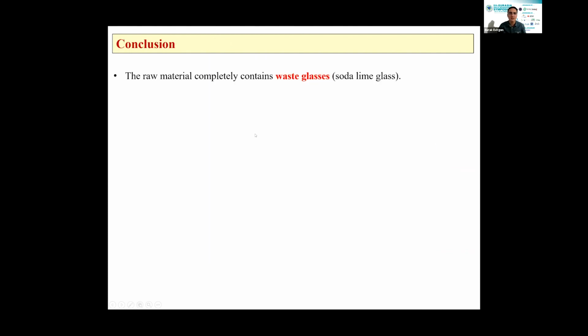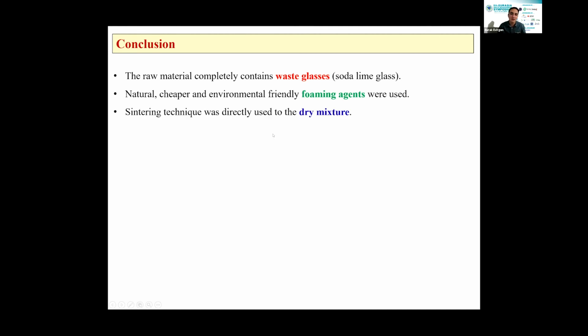And these are conclusions. The raw material completely contains waste glass, soda lime glasses, window glasses, or wet flat glasses. These are our standard glasses. And natural, cheaper, and environmentally friendly foaming agents were used. Sintering technique was directly applied to the dry mixture, and the dry mixture is our another unique point, and operating costs are dragged down since relatively low temperature was applied. Our peak value is around 850 Celsius. It can be reached up to 1.2 thousand degrees in other production processes.